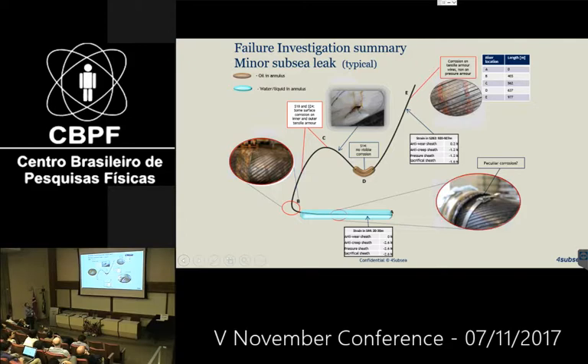Then, very often, if you go along here, if there is a kind of a minor leak in this one, we have seen very often that it is related to some kind of damage near an end fitting. Typically, leak through of the liner or some kind of termination damage. So very often we have a lot of efforts on the liner, but we will not talk much about that here now.